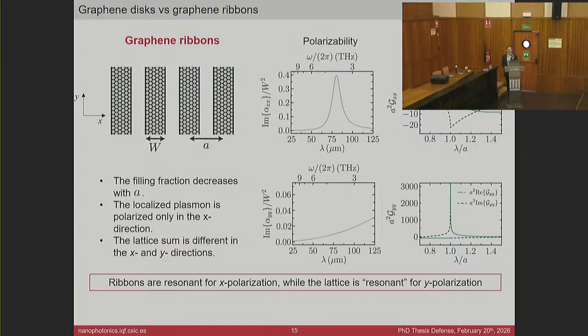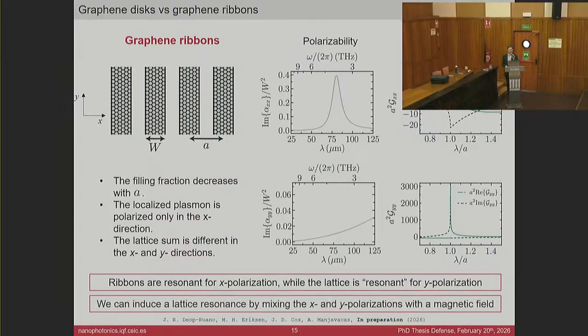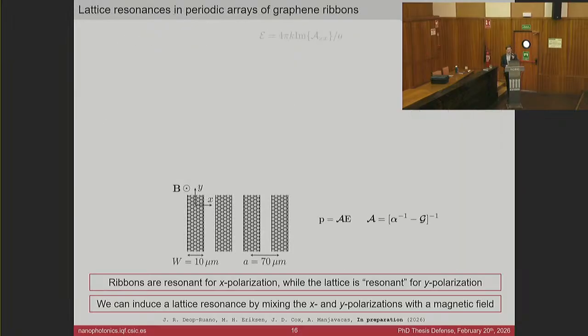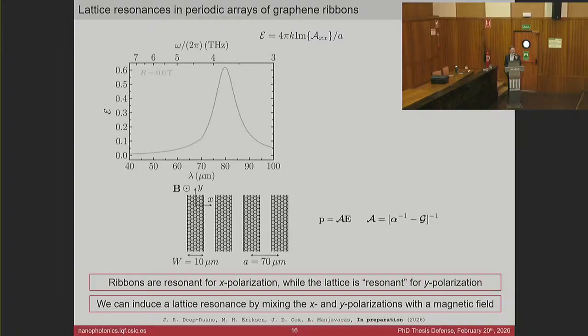So how can we solve that? Well, what I thought is that it would be nice to apply a magnetic field that is able to mix x and y polarizations, and in this way, maybe we can sustain a lattice resonance. Let's check it. We again study the response through the extinction efficiency of our array, and I plot here the results in the absence of a magnetic field. We can see something that looks like a particle plasmon, a broad resonance, and as we turn on the magnetic field, we can observe the emergence of a new resonance with a really narrow profile, a lattice resonance. So this method actually works.